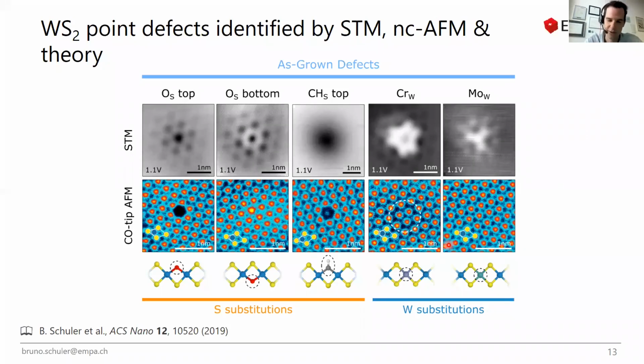And the success rate is fairly big. So I think more than 50% you keep the CO on the tip. And you mentioned that you grow the samples on the East Coast and then you study them in an ultra-high vacuum system on the West Coast. There were no issues with oxygen degradation in the meantime, or did you use a vacuum suitcase, or how did you transfer the samples? So the transfer was usually through air.